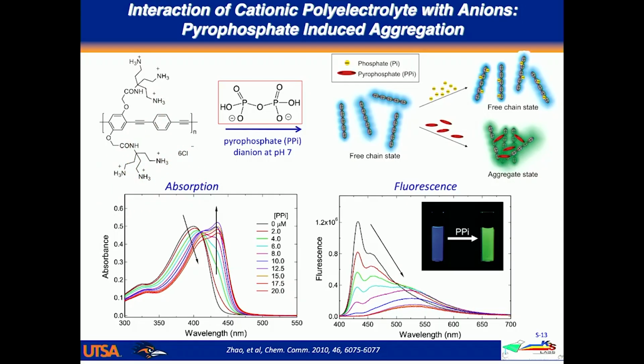The goal we set out when we designed this polymer was to make a polymer that would be very water soluble, taking advantage of the high charge, but also using these branch groups to keep the polymers apart so they didn't aggregate. And it turns out we were successful. This polyelectrolyte in water exhibits the blue fluorescence that's characteristic of the unaggregated polymer.